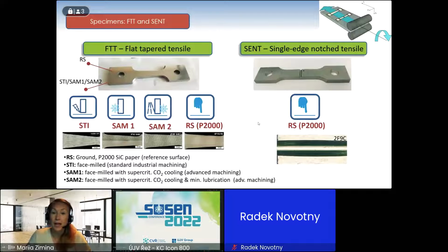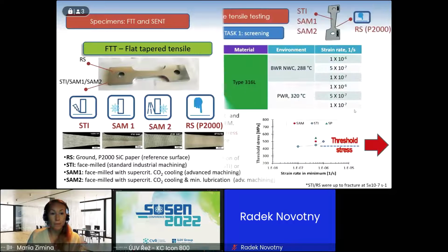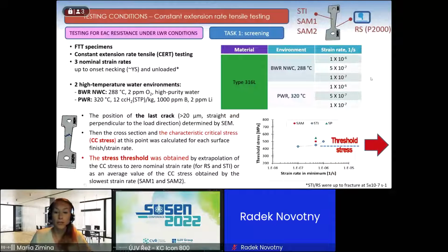And the second type of specimen which was used for the initiation testing was a SENT sample, which stands for single edge notch tensile specimen, and the surface of the notch here was prepared as a reference surface, again ground with a silicon carbide paper. So testing conditions for this program were chosen as follows.